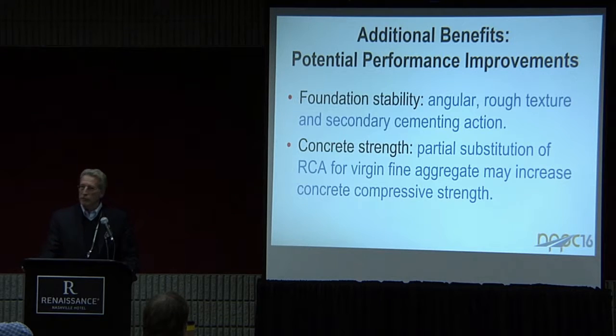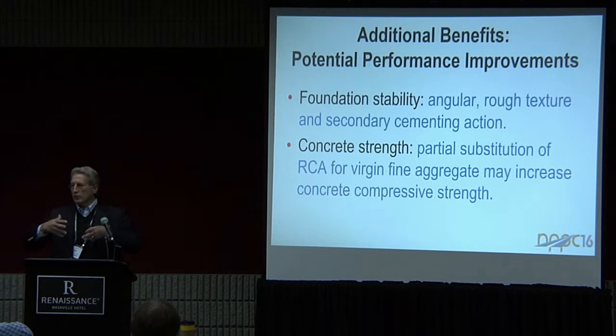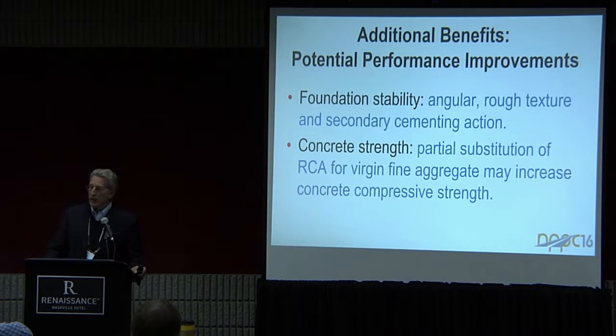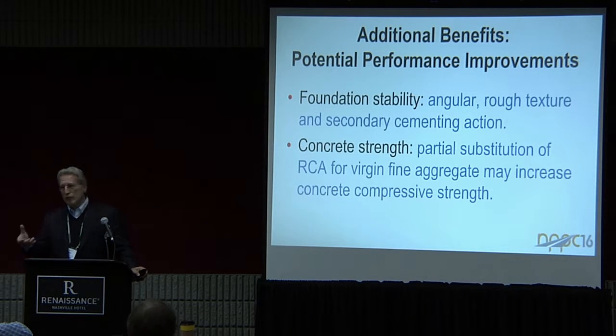In foundation applications, many states have found that the crushing of the concrete exposes previously partially hydrated or unhydrated cement grains. When you lay this material out with those freshly exposed grains, over a period of time water infiltrates the pavement system and causes those grains to rehydrate, to do additional hydration, and we see some stiffening of that base. So you actually have a stiffer base for the same gradation of a recycled material as you would with a natural aggregate foundation material. That can provide some benefits in terms of perhaps reduced thicknesses required for the layers that go above that base layer.